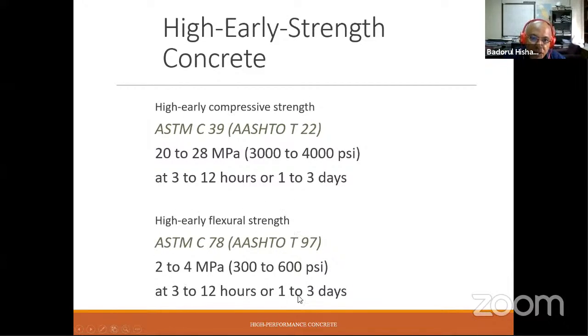High early strength in flexural strength, between 3 to 12 hours, you can achieve between 2 to 4 megapascal. In conventional concrete, this will be achieved in 28 days or 14 to 28 days, which is a longer period of time.